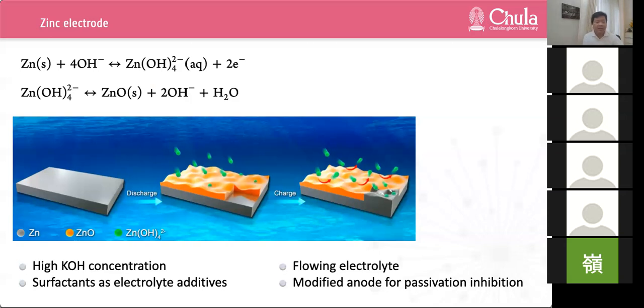In practice, the actual energy density of zinc air battery is about 200-something to 300 watt-hour per kilogram of zinc, lagging far behind the theoretical value. Well, the theoretical is more than 1,000 watt-hour per kilogram, which remains a challenge to reach and requires substantial effort for development. The low utilization rate of zinc, which is due to the passivation of zinc electrodes in alkali electrolytes, is one of the important reasons for the difference between theoretical energy density and the actual energy density.